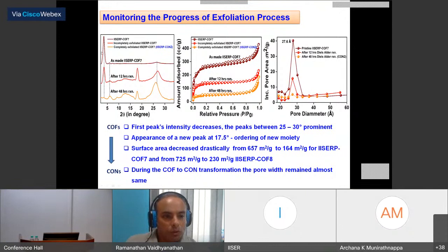So the H00 reflection, which is a characteristic reflection of a COF, starts to lose its intensity because the atoms contributing in the AB plane are now going to contribute less when this material gets exfoliated. And this makes the 00L reflections become more prominent as the intensity of the H00 reflections goes down. And also you can see another important signature, that there is a new peak occurring at a 2 theta of 17.5, which is not present in the parent COF. And this peak is due to the ordered insertion of the maleic anhydride groups into the structure.